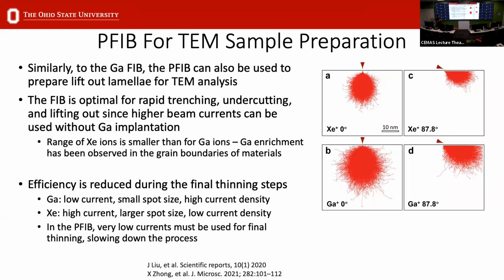The PFIB is also available for TEM sample preparation. You can use it the exact same way as the gallium FIB. There are just a couple of differences in the interaction of xenon versus gallium in your material. With gallium, you might have to deal with gallium implantation. If you have a polycrystalline material, you might find gallium segregates to your grain boundaries, which could be an issue in some cases.